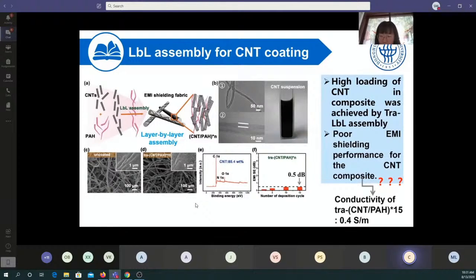This coating also shows a hierarchical structure where the CNT were coated with the polymer, and moreover, the coating is around 3.9 micrometers thick around the fiber. This thin coating results in flexibility and air permeability of the coated fabric. These two characteristics are very important for the practical use of the fabrics. And also, using this method dramatically increases the conductivity of the conductive fabrics.